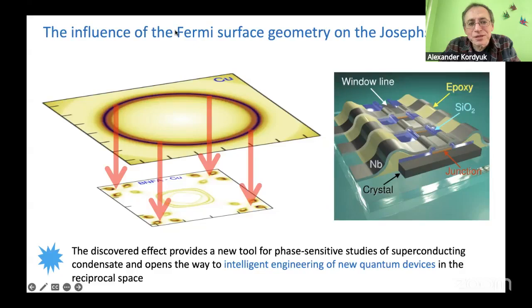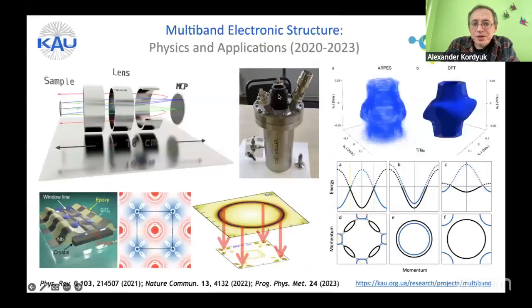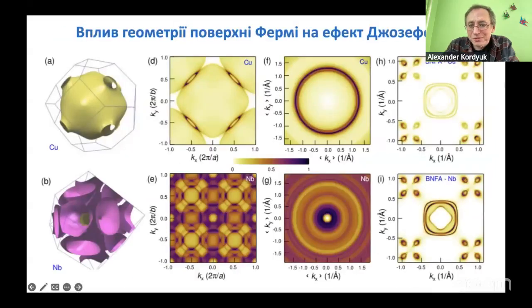And this is Alexei Kalinyuk from us. He spent there 3 years to develop this technique just to make a junction between niobium and iron-based superconductor. Of course, he didn't spend the whole time there, but it is their equipment and quite a large experience. Therefore, I understand it is complicated. And niobium is a very good getter. It absorbs easily everything, so niobium is not the best thing for this. We have another solution, molybdenum rhenium, which is much more stable and more technological. Therefore, if we develop this direction, we would look for another material, not niobium.